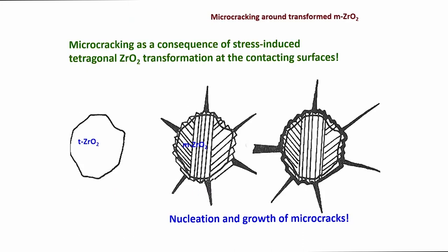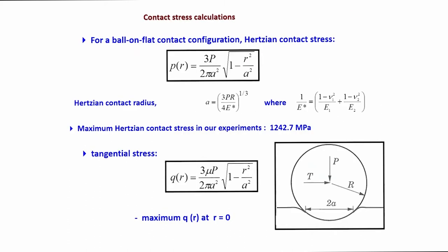So, tetragonal zirconia to monoclinic zirconia phase transformation under tangential stress conditions is more favored in the absence of microstructural constraints. And again, microcracking around transformation toughened zirconia: you can see this is the tetragonal zirconia, and then when it transforms to monoclinic zirconia, it causes these microcracks, which can release from the periphery of the transformed phase.